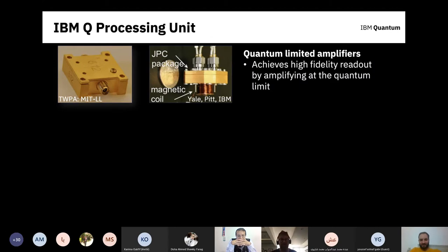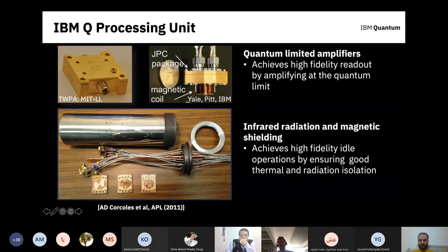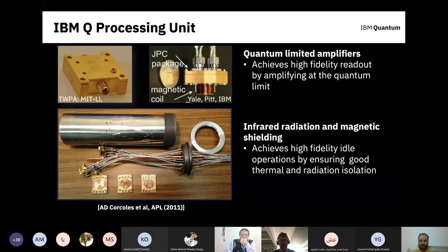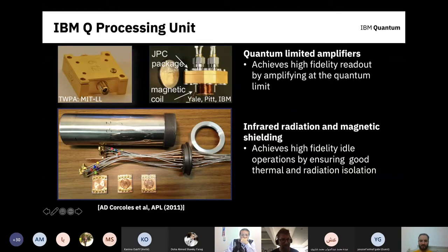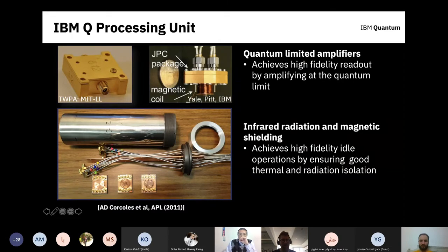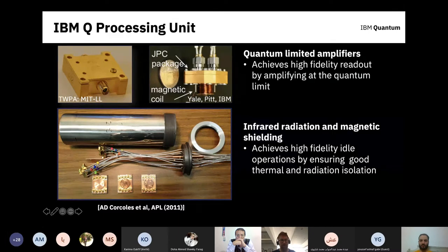We also have to shield these qubits very carefully from the outside environment. We package the qubits typically in a printed circuit board with transmission lines that deliver signals to and from the chip through coax cables — just like regular coax but smaller to support higher frequencies. Everything lives inside a can made of cryoperm, which expels magnetic fields so they won't disturb the superconducting qubits. The RF lines also need to be light-tight, so we surround everything in Ecosorb — an iron nanomaterial composite epoxy — to shield signals and prevent any infrared light from getting into our devices.